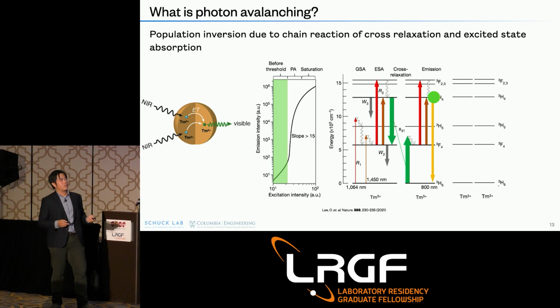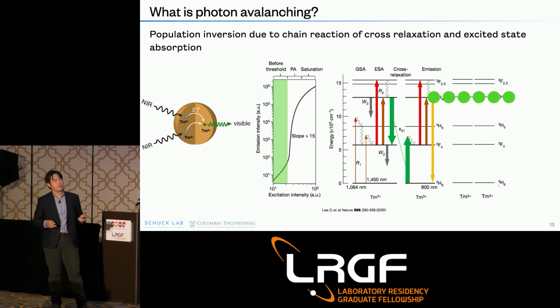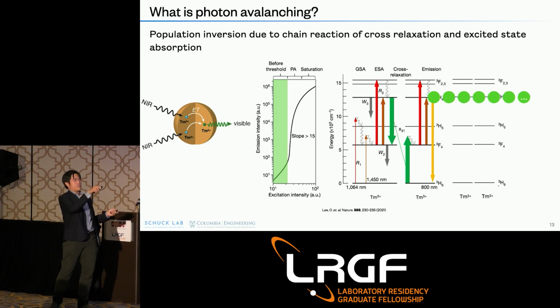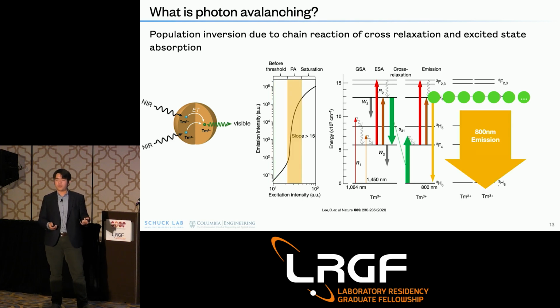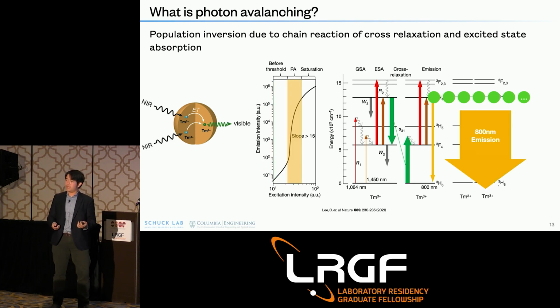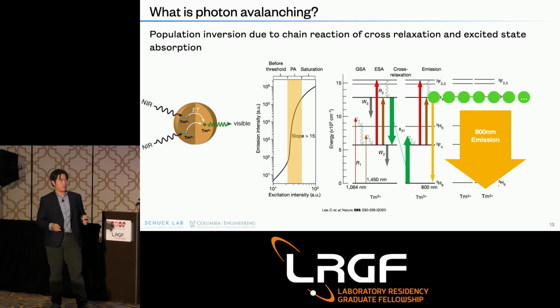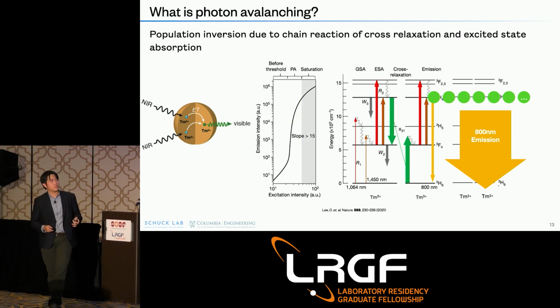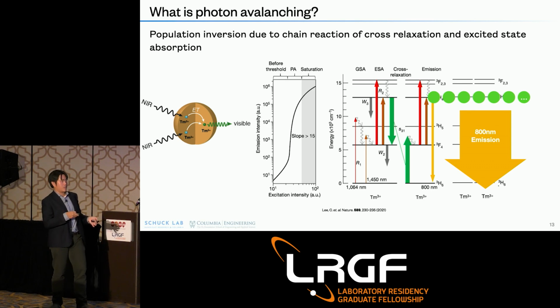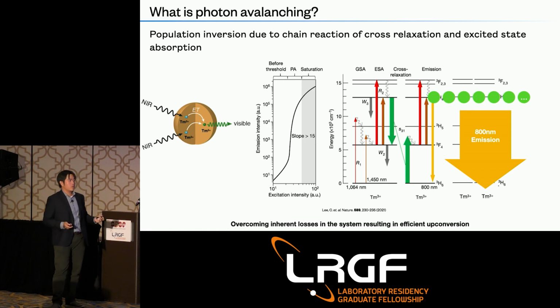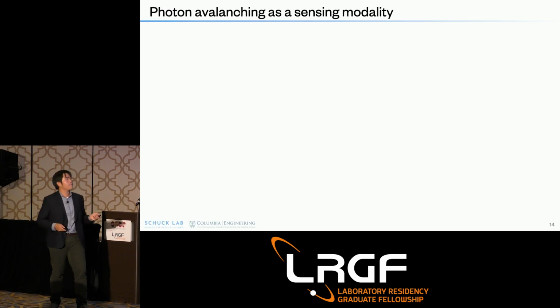Eventually you start building up this population of 800 nanometer emitters in the second level, and eventually you run out of ground state ions to excite, and it needs to emit all at once in the 800 nanometer energy range. And eventually your material saturates and you start to lose this nonlinearity that we talked about earlier. But ultimately, what you're getting is you're overcoming a lot of the inherent losses in your system, resulting in efficient upconversion. So photon avalanching is a form of upconversion, just a very efficient one.